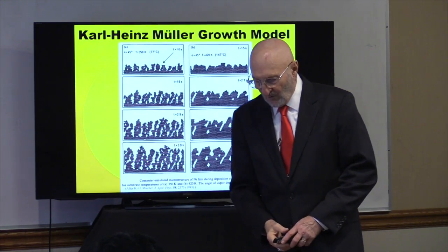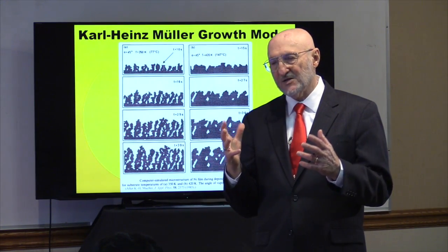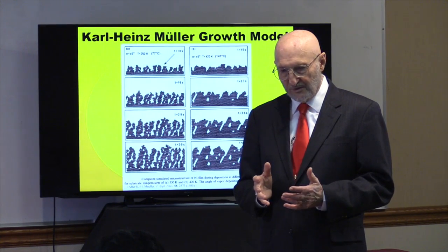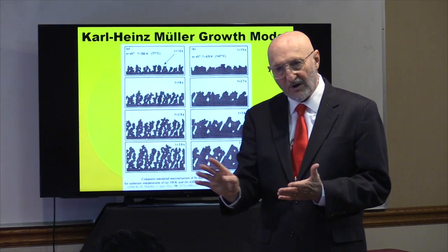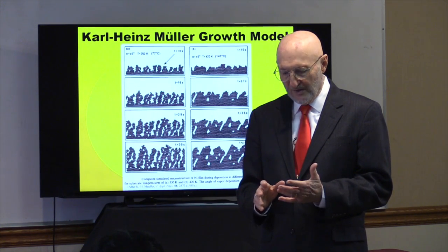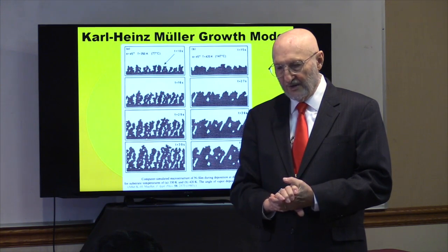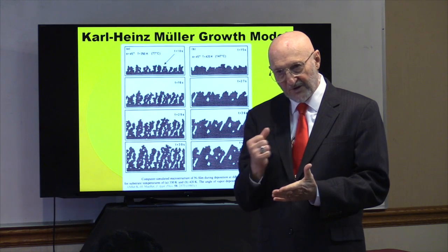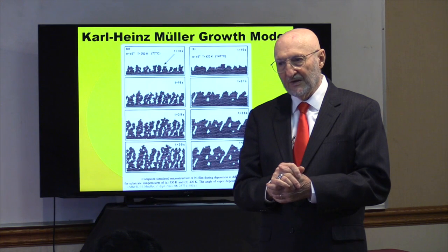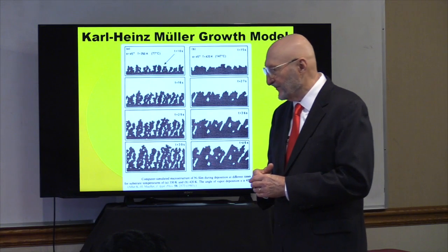So one example is, for example, I deposit magnesium fluoride on glass. If I do that at room temperature, take it out of the chamber, I can wipe it off with my finger. It has no adhesion, no hardness. If I put it down at 300 degrees centigrade, I can take it out and do an eraser rub test, 50 strokes or something like that, no problem. So this is an illustration of what's going on there.